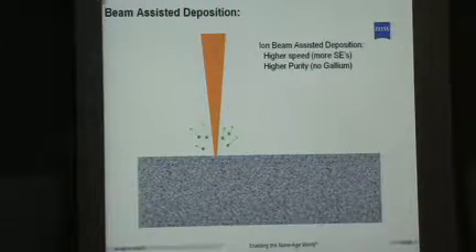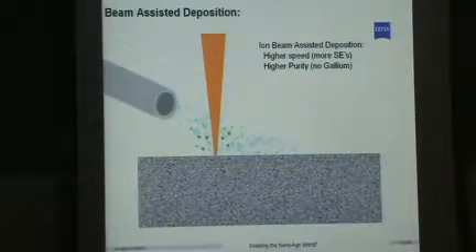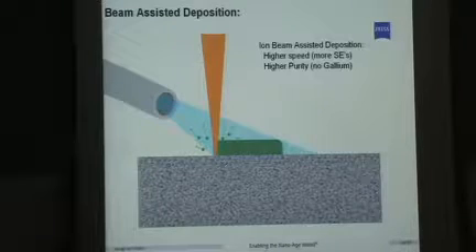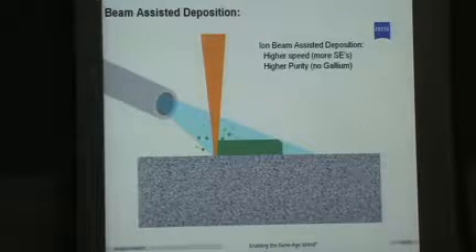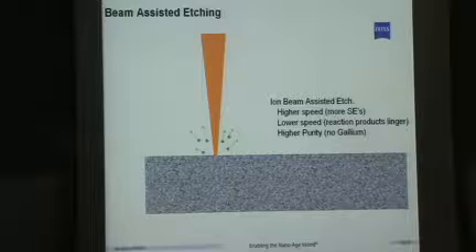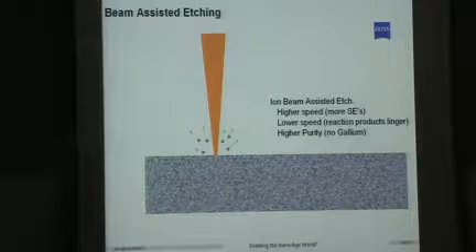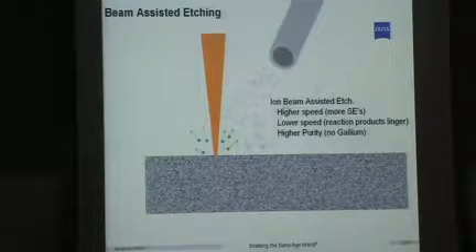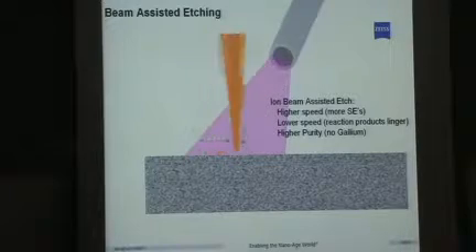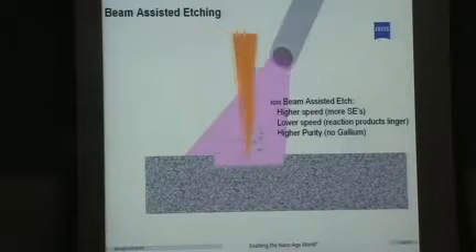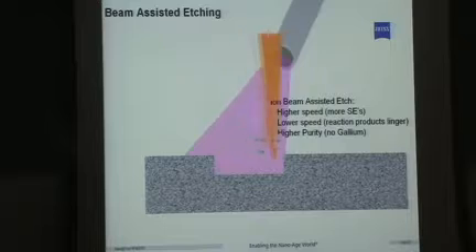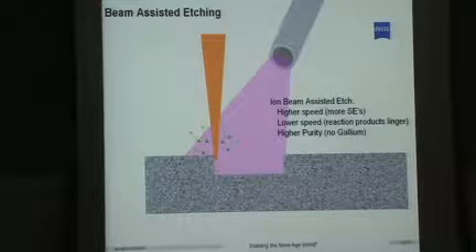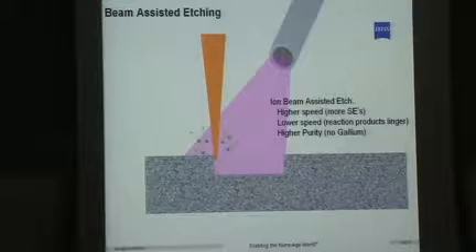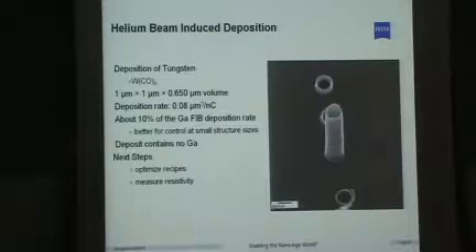There's also beam-assisted deposition. So if you add a gas, flood it in, while you're rastering your beam, you can build something up. Or if you do the opposite, if you add a corrosive gas and pattern it with the beam, you can actually cause material to be removed in that area. Yes, helium will sputter by itself, but it's not the heaviest of the noble gases. It doesn't sputter a lot, so you can really exaggerate this effect with another gas.